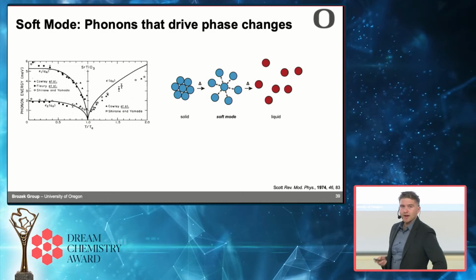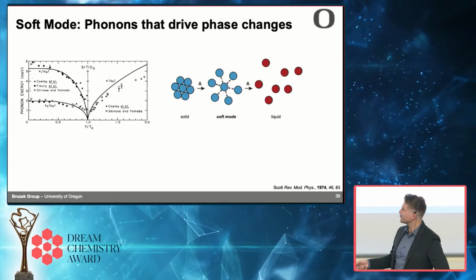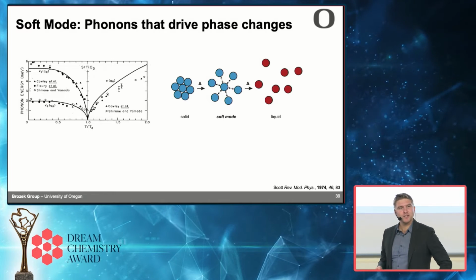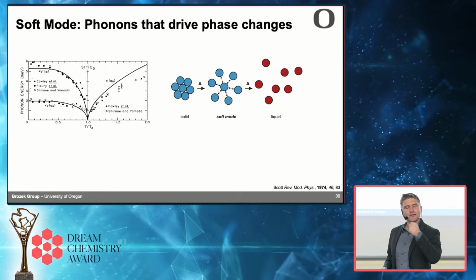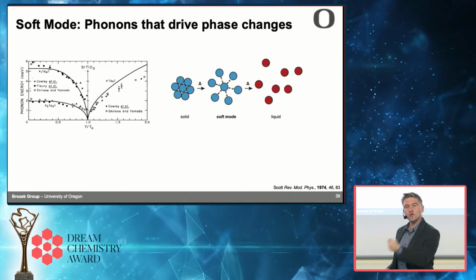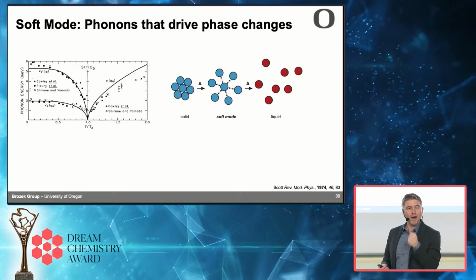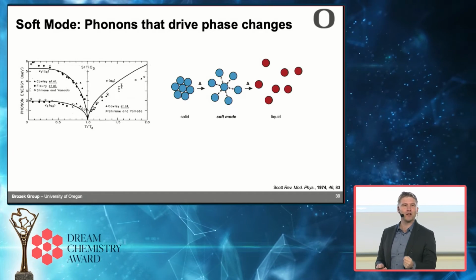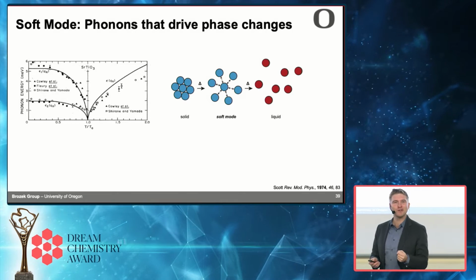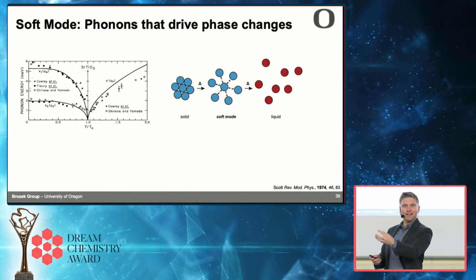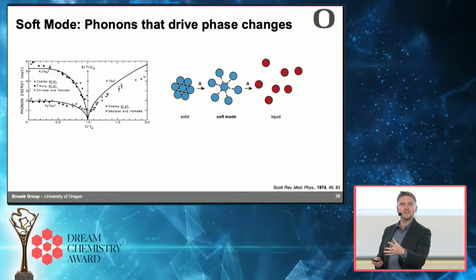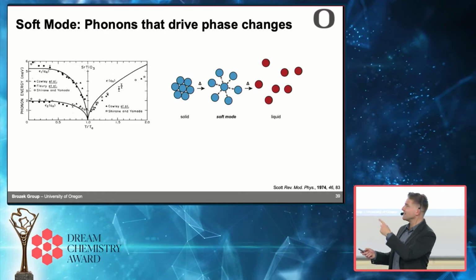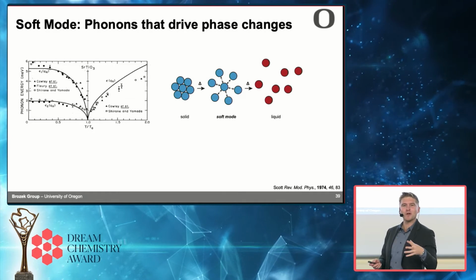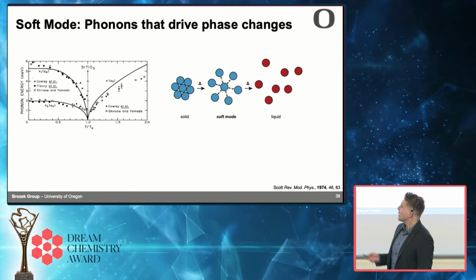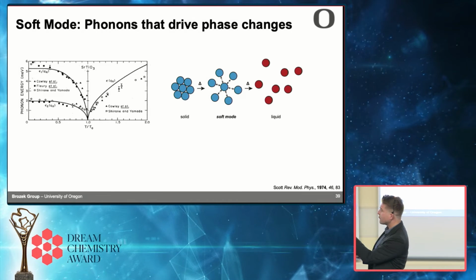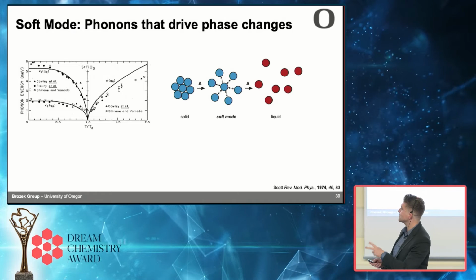A soft mode is a vibration. So a vibration in a crystal is called a phonon. So it's a vibration that as it vibrates, it moves the position of the atoms so badly that it causes the material to fall apart. So if you've ever seen the cartoon of the opera singer singing and the wine glass vibrates, it resonates, and then it explodes, that's sort of my analogy here, except this is a reversible process and the exploding wine glass is not reversible. But this is data of two soft modes for a very common material, strontium titanate.